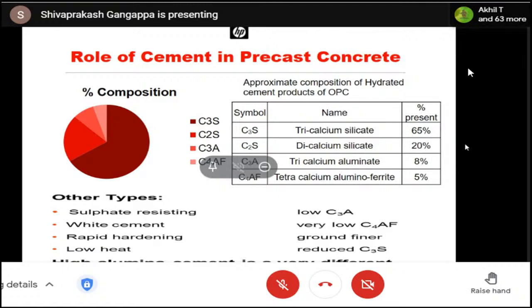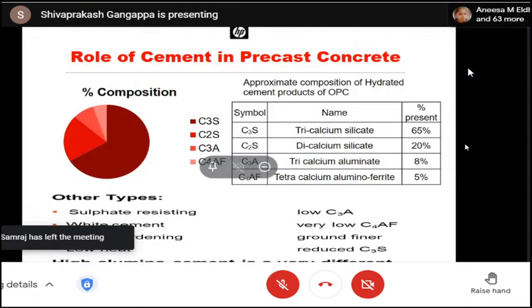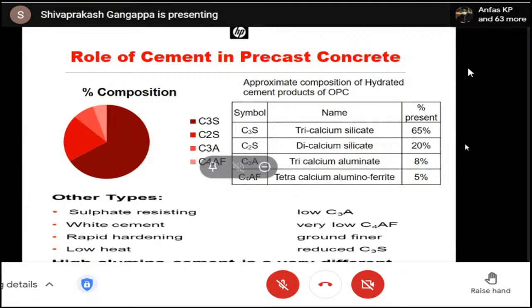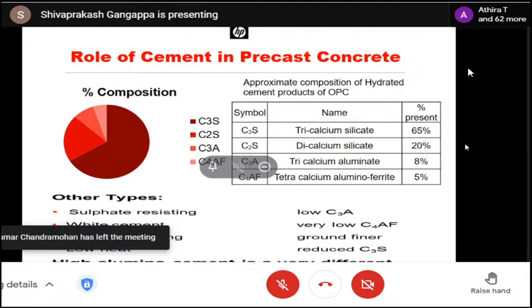The very first compound which starts hydrating is the aluminates. Aluminates basically bring the shape of the concrete, but they will never help in contributing to the strength. Your strength contribution always comes only from silicates. Silicates maximum already we have about 85%, nothing more we can have, but we cannot produce a cement without aluminates either. Silicates will take their own time to hydrate, but initially we are supposed to get the shape of the concrete, whatever mold we have placed the concrete in, to take that shape, aluminates are very much required. So in a standard OPC, you will have about 85% silicates and about 15% aluminates. Now, what is the objective behind discussing this particular subject?